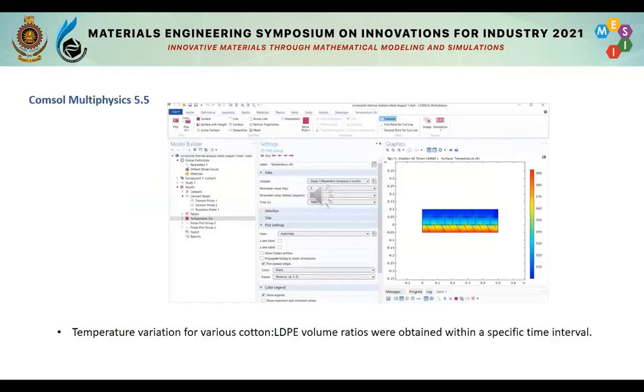As I described in the previous slide, we have kept two temperature probes, which are at the top and the bottom surface. The bottom surface was kept at a higher temperature while the top surface was kept at room temperature, and with time the temperature change can be generated using the COMSOL solver. So here in this figure you could see how the temperature change has occurred.